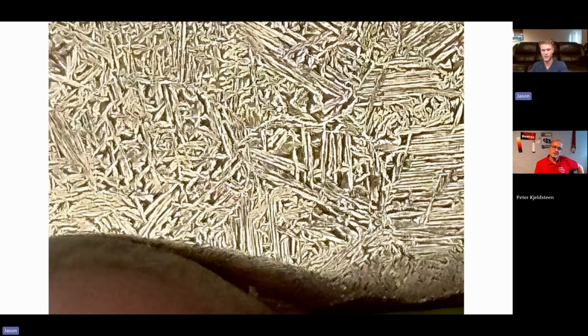And so that's why large beta grains are important, because if we had small beta grains, one, these alpha plates would be very small. We wouldn't be able to see them. And two, there'd be so much variation everywhere that we wouldn't be able to see that symmetry. So something that I really want to try with the electric furnace is growing these beta grains to be very large. And so we can see much longer alpha plates, as well as much more wide-scale symmetry.